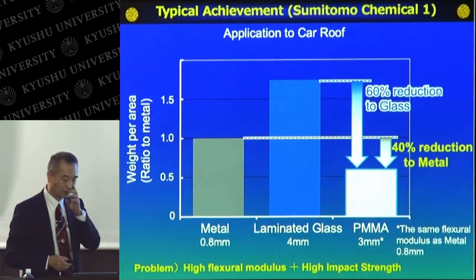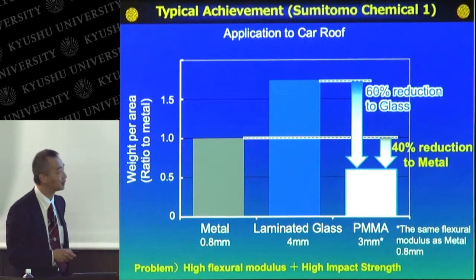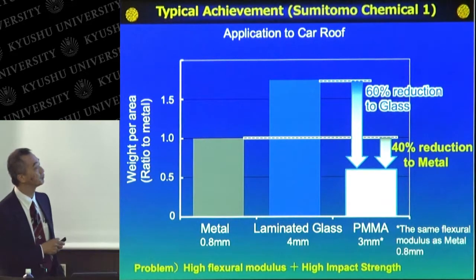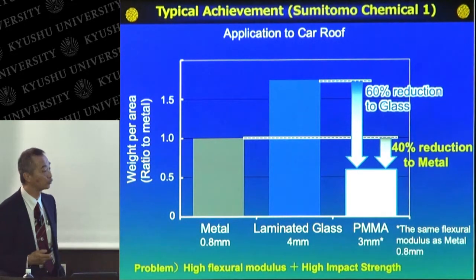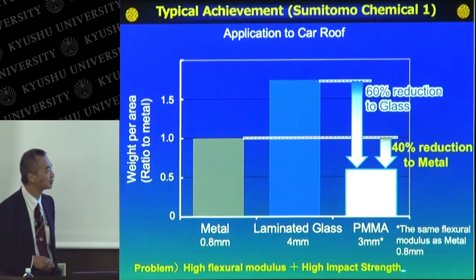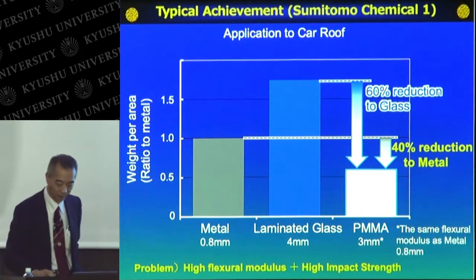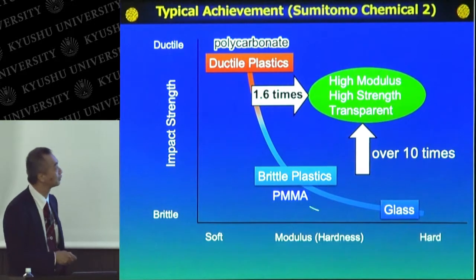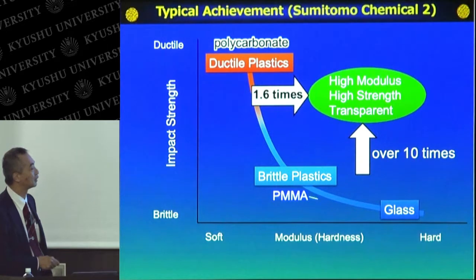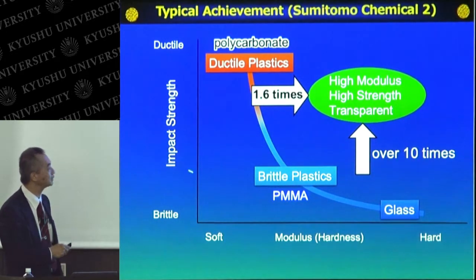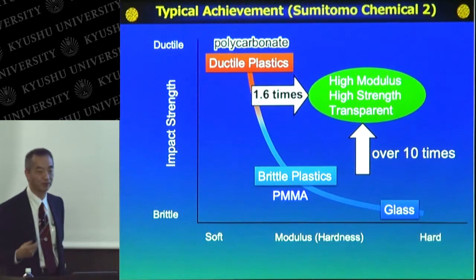And next, I'd like to show you another achievement from Sumitomo Chemical. They tried to develop a transparent resin for car roofs. When the car roof is replaced with a transparent resin, the weight is reduced about 40% compared to metal and 60% compared to glass. But the problem is that high modulus and high impact strength have a trade-off relation, as you know. This shows a typical trade-off line of the transparent resins. And the impact strength and modulus or hardness have a trade-off relation.